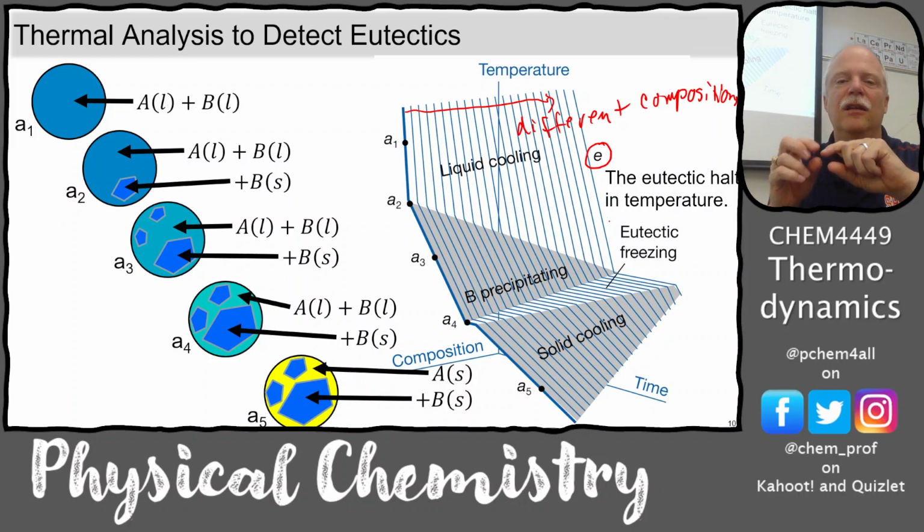And then you get the leads of the circuit up to that temperature so that the solder will wet the leg of the circuit, chip, and wet the little pad that it's sticking on. And then you pull the iron off and it freezes. And now you've got a metal-metal bond. So that's how soldering works. We use eutectics for solders. You can make really low melting eutectics with lead, but obviously for health reasons for the people doing the soldering, they wanted to get away from lead. So lead-free solder is a really big deal. They put in silver and tin and a bunch of other metals and find those eutectics that have really low melting points.